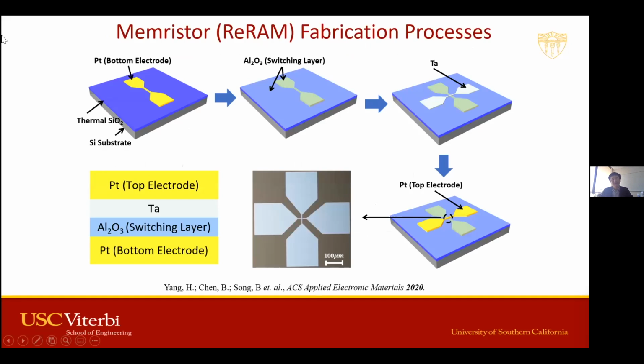So this is the specific memristor structure we are using right now. We have a top electrode and a bottom electrode, both made of platinum. The switching stack consists of a tantalum layer and an aluminum oxide layer. The aluminum oxide is deposited using atomic layer deposition. The fabrication process is fairly straightforward: just put down one electrode, then put down the switching stack, and then put on another electrode.